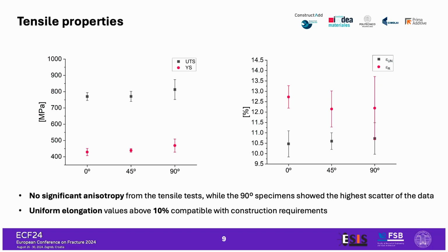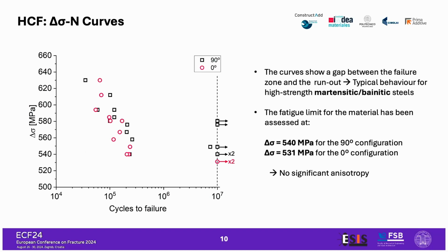So very good results in terms of ductility for this material. And then from the fatigue test, we assessed in the first instance the fatigue limit. So plotting the delta sigma against the number of cycles to failure. So the fatigue limit at 10^7 cycles. Also in this case, if you look at the points, we see that they overlap basically.